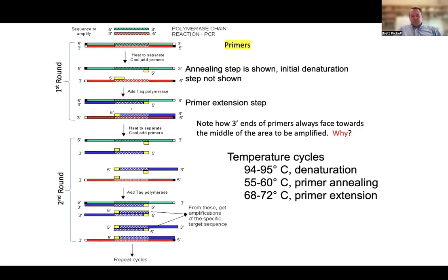So it's important to remember the temperatures for these. The first step, denaturation, where you're separating the strands, that happens at about 94 or 95 degrees Celsius. The primer annealing, that needs to be a little bit lower. So that lets the primers find the exact right sequence where they're going to stick. And there's going to be millions of primers in this tube. Not nearly as much template as there are primers. So the primers are going to anneal in the 60 degrees Celsius range. And then extension, the polymerase works best at about 72 degrees. So that's going to be the best one for that.